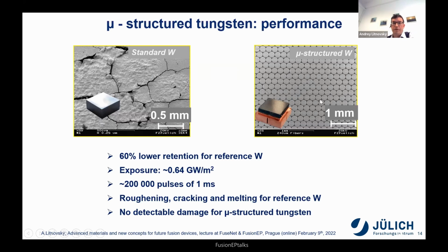Without detectable damage. To be honest, also the deuterium retention was larger, which is not good for such a structure, but the operating temperature of such materials will be high enough to outgas this deuterium. So this actually showed the incredible performance under repetitive high power loads.